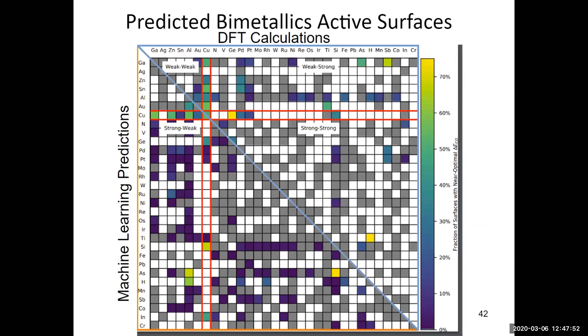So we can go and analyze different combinations. In the upper right, these are things that we confirm with DFT. In the bottom left, these are things that we predicted with ML. Anything that is white is a bimetallic combination that the Materials Project said they don't have a stable crystal structure for, or if they did have one, we weren't able to get it to converge with our own settings. And so I think it's interesting how much white space there is in composition.